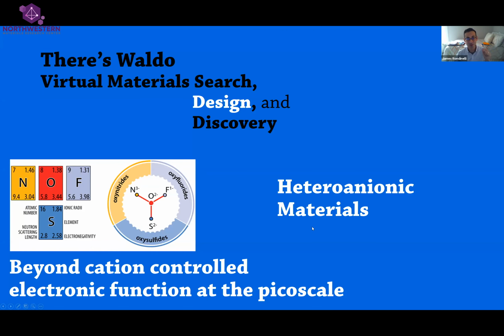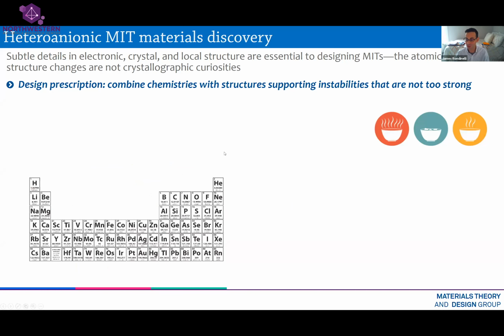And so what we're going to do is not use cation substitution, but use a very alternative strategy, which leverages what are called heteroanionic materials. And this is, in fact, the focus of IRG2 in the MRSEC at Northwestern, in which you're participating. And here we are looking at a whole range of compounds which have multiple anions. The ones I wanted to highlight for you in this talk are what are called oxynitrides, where you take oxygen and nitrogen and you make a transition metal compound out of them. And the reason you can do this is because the ionic radii of these two anions is fairly similar. And so they can form compounds in which the anions comprise both oxygen and nitrogen. And so this is the design challenge that I'm going to tell you about.